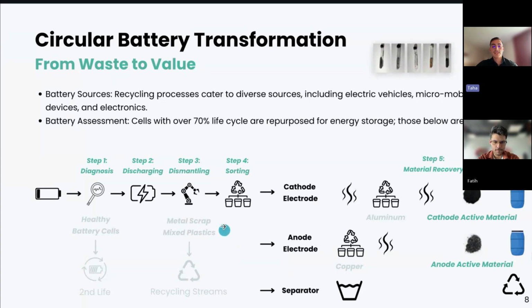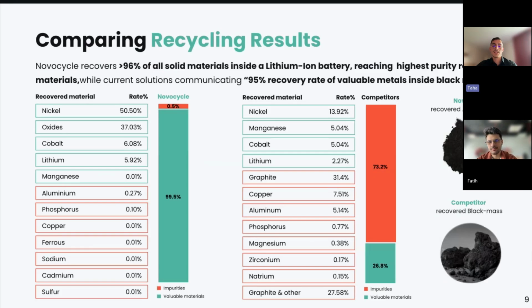The metal scraps and the mixed plastic coming out of this process are going to different recycling streams, to metal recyclers and plastic recyclers. The cathode and the anode are entering a gasification process in order to remove the electrolytes and binders, after which we can separate the active materials from the collector foils. So at the end, we have high purity cathode active material recovered and high purity anode active material recovered. And the separators are entering a washing process, and after that, going into the separate plastic recycling stream. And with that, I would hand over to Fatih to share a little bit more details about the material compositions.